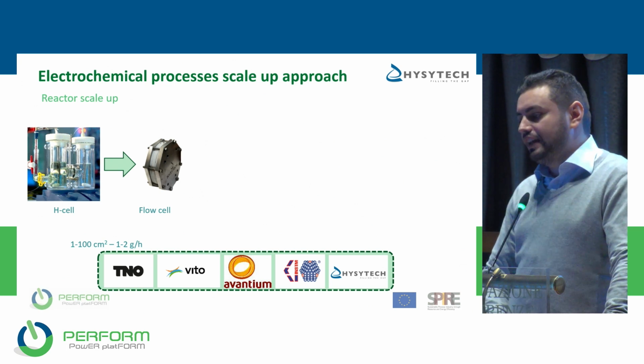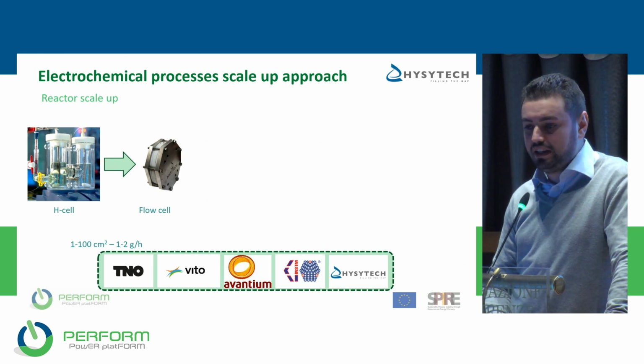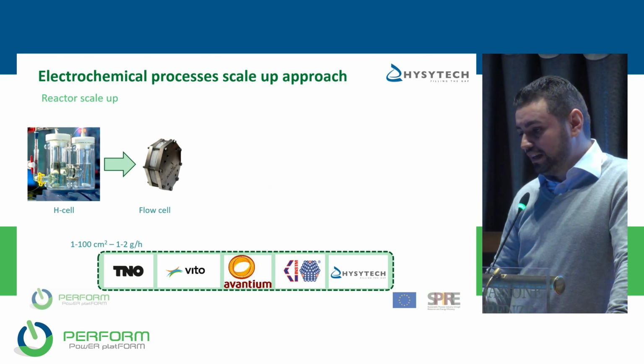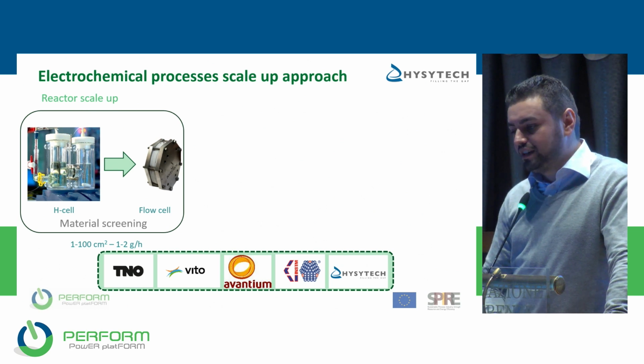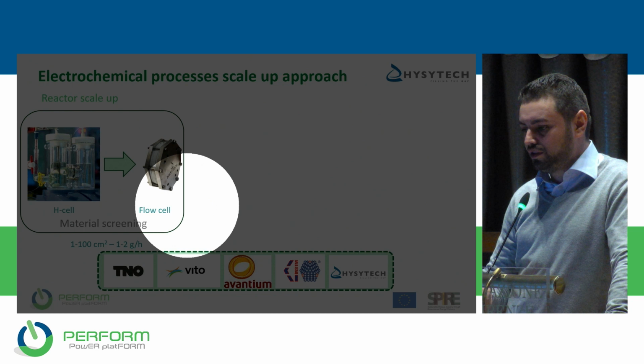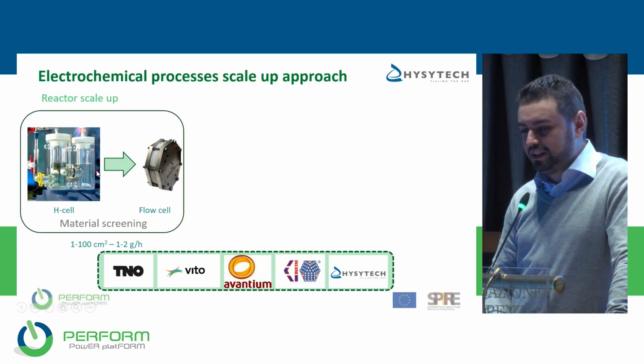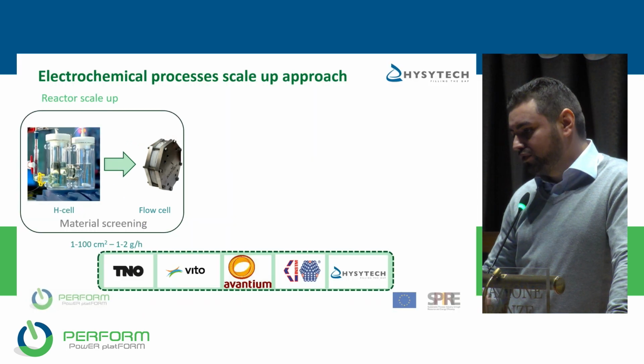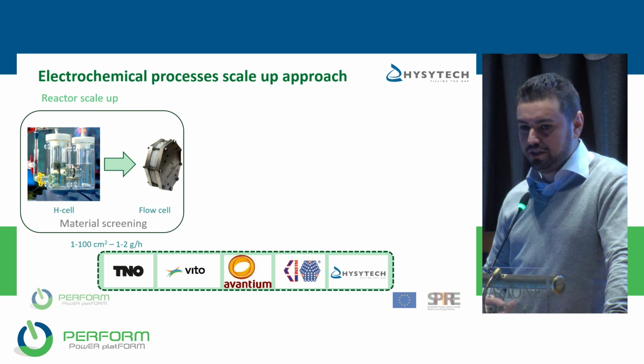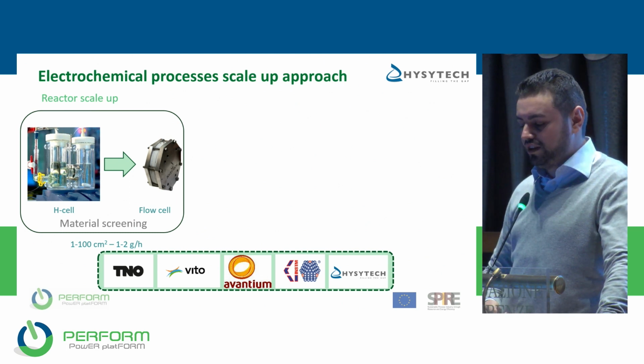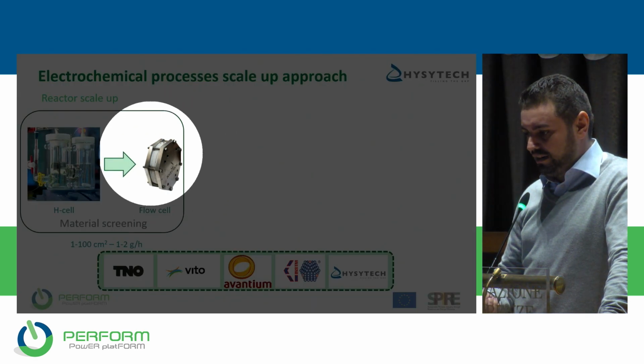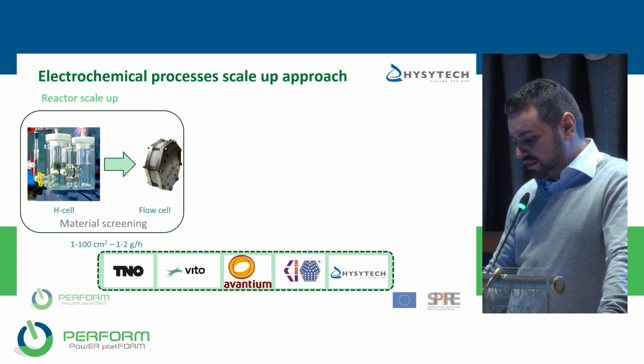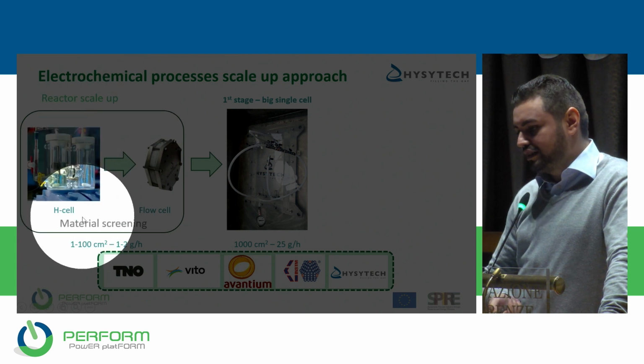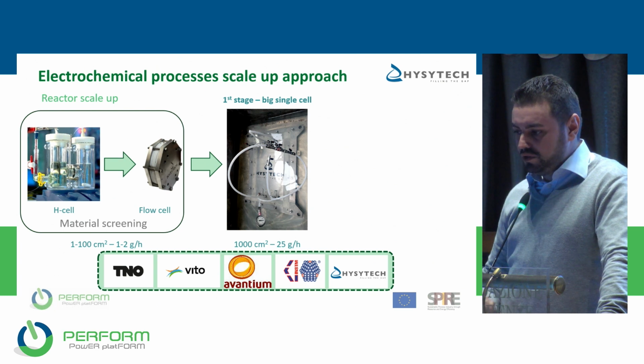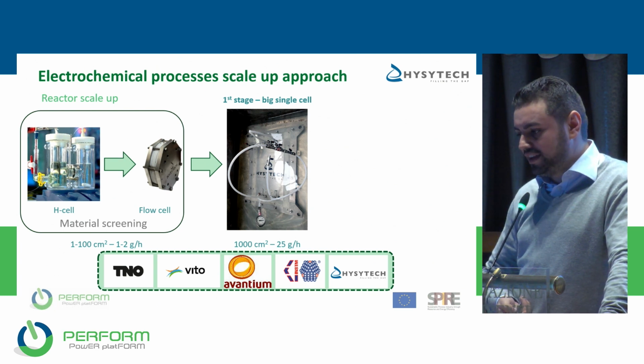As mentioned, for the reactor scale-up, usually you start with very small reactors. Typically, when you start with the materials screening, you use H cells, in order to perform fast electrode material screening, then you move to flow cells. Why do you move to flow cells? Because it's basically what you are going to do industrially. Industrially, in order to increase the throughput of your process, you need to move to a flow cell arrangement. This is still at the lab scale, so between 1 and 100 square centimeter, and then you move to bigger and bigger cells.